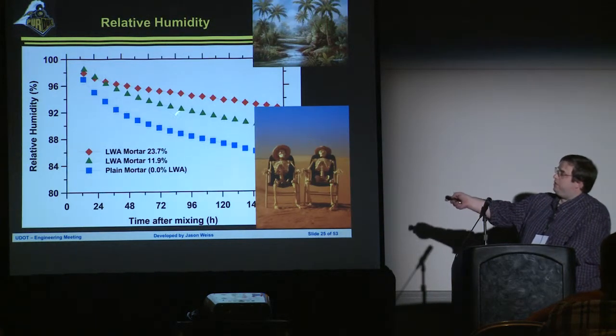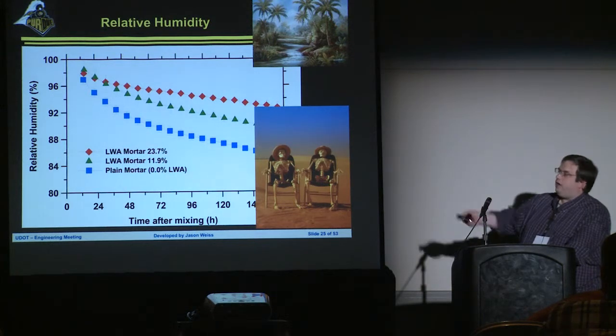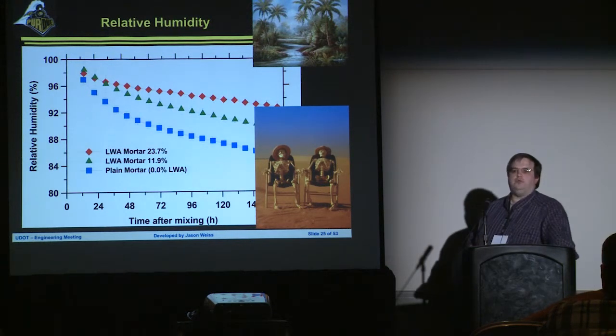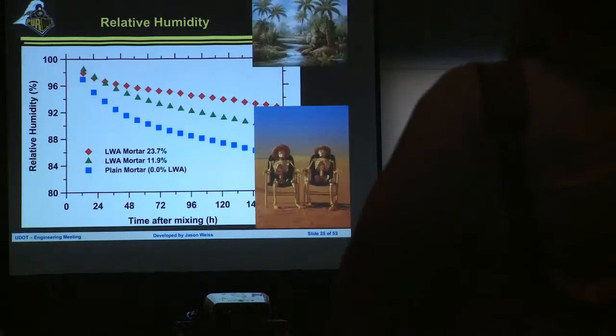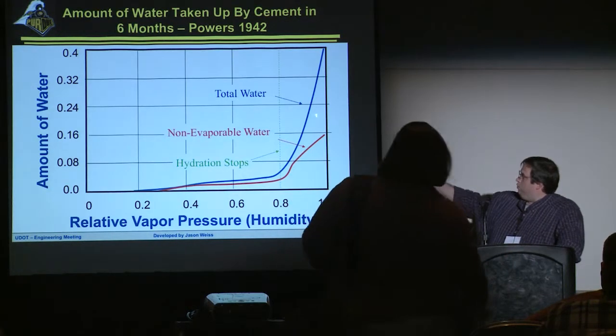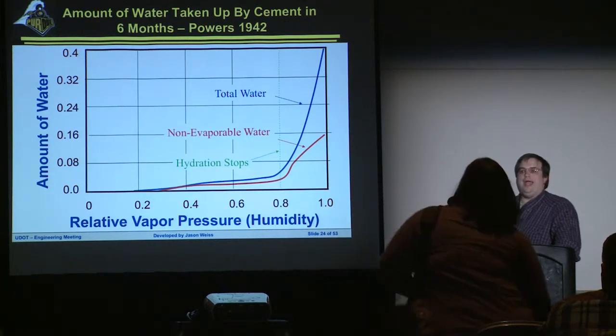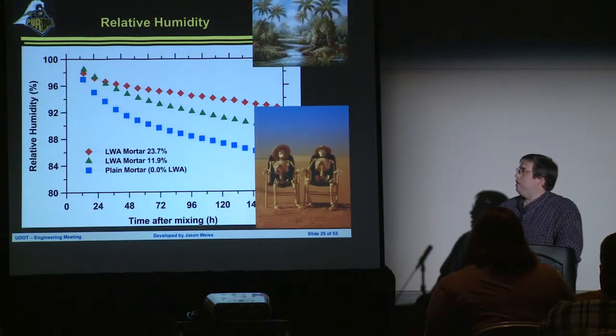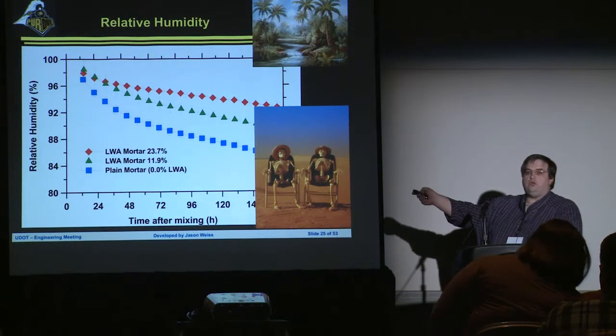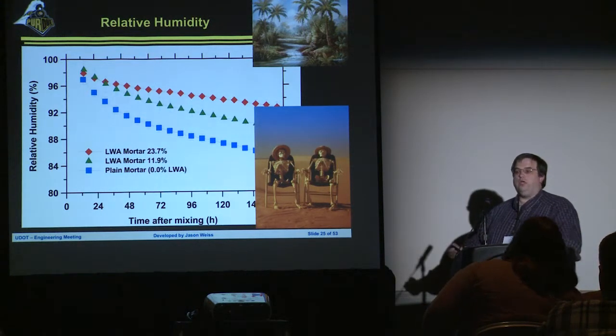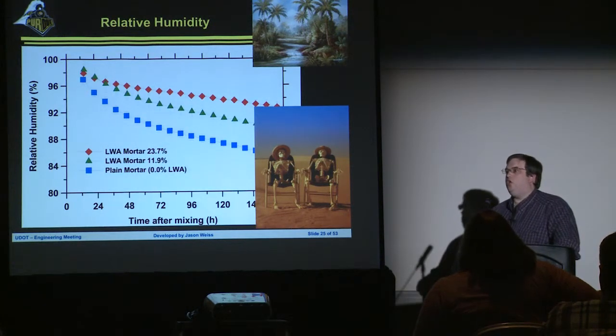All right, so here's our conventional mortars. Our plain system may drop the relative humidity down around 85% at the end of the first week. 85%, you're down in this range here. Our internally cured mixture, we're up around 95%. We're way up in here. More reaction going on in the system because we're supplying internal curing water. Right? When we get more internal curing water, we keep the system moist, we keep the system reacting, we keep hydrating the cement, which means we're going to have lower porosity in the overall system.